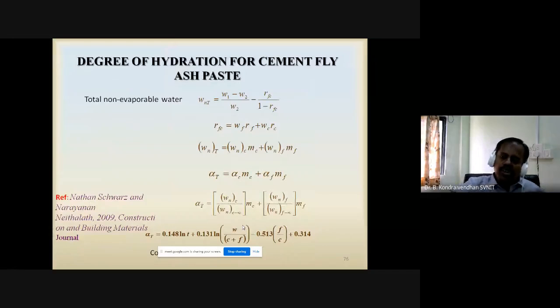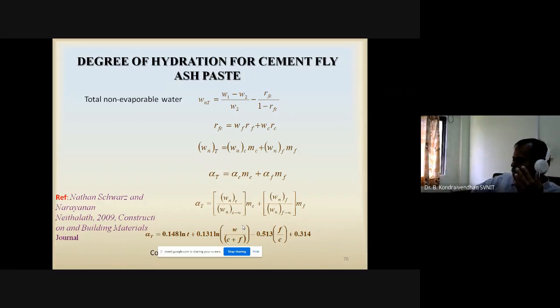Then again, how to determine the degree of hydration for the cement fly ash paste? In case of OPC, it is very simple, because Powers already developed something. There is combined water for the cement. We know 1 gram of cement has 0.23 gram of combined water. That's why we can determine it quickly without any hesitation.